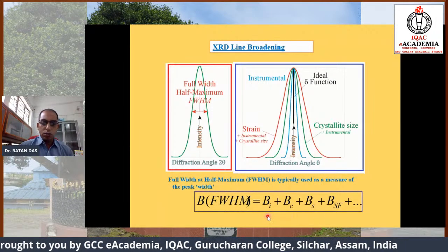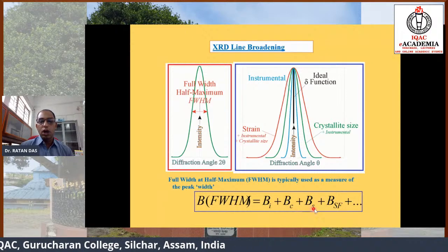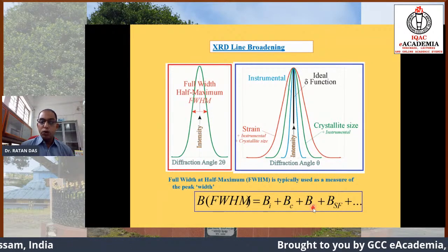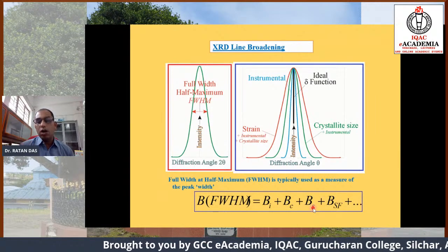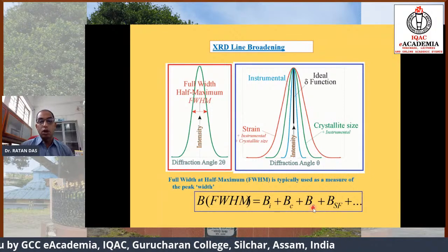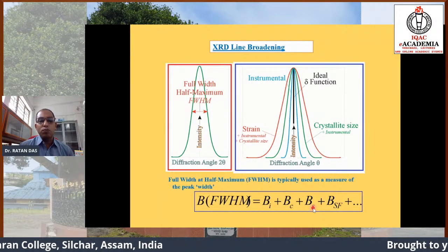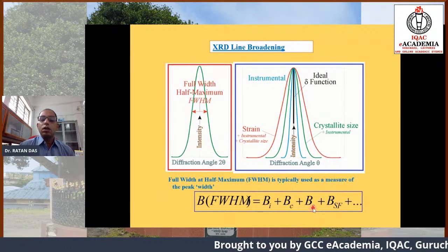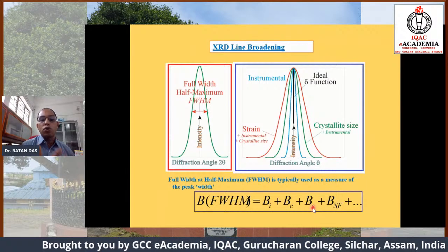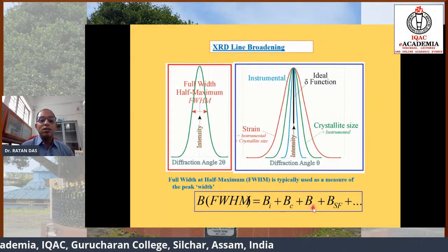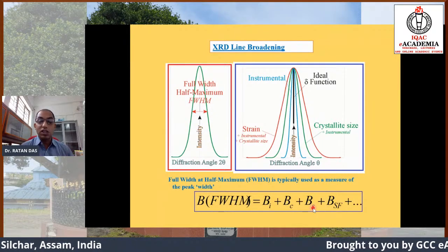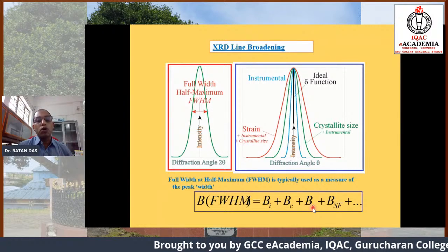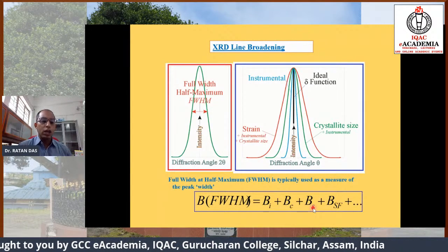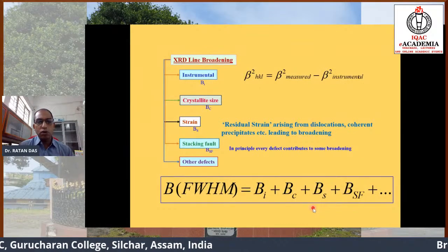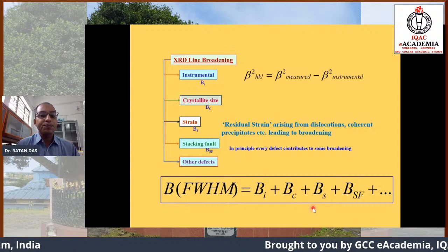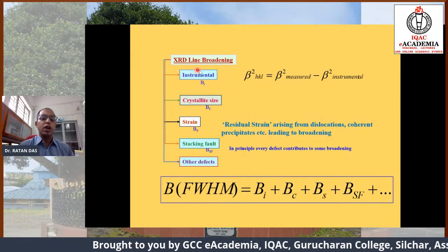But there are other effects also. Instrumental broadening, I have told, crystallite size, I have told, and the strain also I have told. But because of the presence of some defects, suppose if we dope a semiconductor sample with another atom, then that arrangement also gets distorted because of the doping, and some extra strain comes into effect, and that's why we may obtain extra broadening. Let me go into the next slide. I shall tell about all the details later in my slides. So what I have told you is that in the X-ray diffraction pattern, we have instrumental broadening.